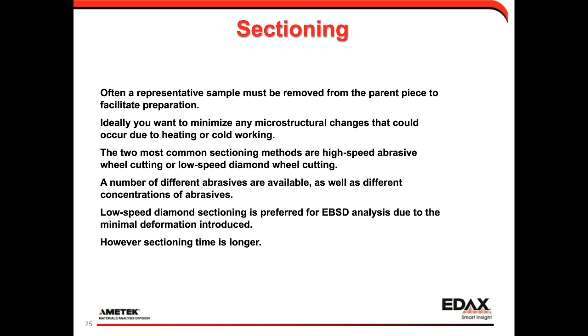As we sample a material from a parent piece to a smaller piece, we really want to minimize any microstructural changes that are going to occur due to the sectioning. The two most common methods are usually a high-speed abrasive saw or a low-speed diamond saw. Really, I'd say for EBSD, the low-speed diamond sectioning is preferred because it minimizes the deformation that's introduced. However, using a diamond saw, of course, will take a little bit more time than a high-speed saw.